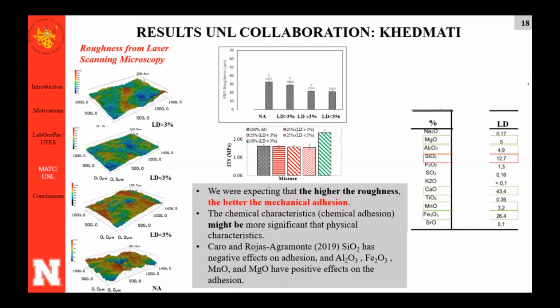So I went to my chemical results again, and what I observed was that my slag has a lot of those good components, good oxides. Calcium 43%, silica 12%, aluminum, magnesium 5%. Silica is negative, and it still has 12%. But my natural aggregate was a granite, which is rich in silica, and that brings the negative effect. So now it starts to make sense.